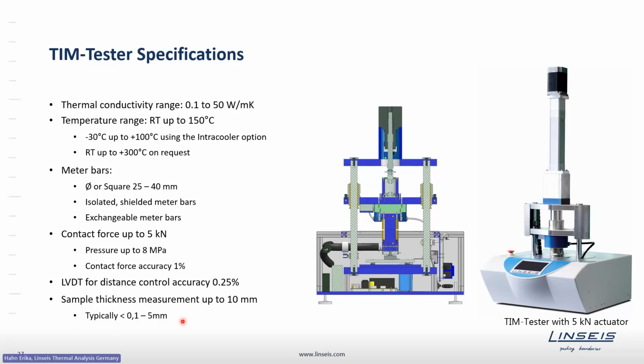Most of the samples we test are quite thin, so that the sample thickness is mostly ranging from 100 micrometers up to 5 millimeters. Basically, thicker samples can be measured as well. Before I mentioned that we measure the thermal impedance of the material, so the sum of the thermal resistances as well as the contact resistance. But in practice, this contact resistance is not of interest or should not be included in the end result.